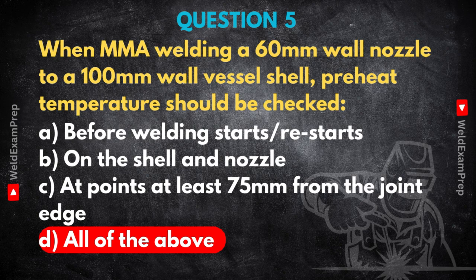This really brings up an important point. Why is such a rigorous, multifaceted check absolutely critical, especially in heavy fabrication like this vessel scenario? What are the real-world consequences if an inspector misses something or if it's not done properly? The consequences, honestly, can be catastrophic, especially with thick sections. If preheat is insufficient or not maintained or not checked properly, you're basically setting the stage for potential failure. Rapid cooling in these thick sections leads to hard, brittle microstructures in the HAZ, and crucially, it traps any hydrogen that might be present. That combination significantly increases the risk of delayed hydrogen cracking. Cracks that might not even appear immediately, but days, even weeks later.